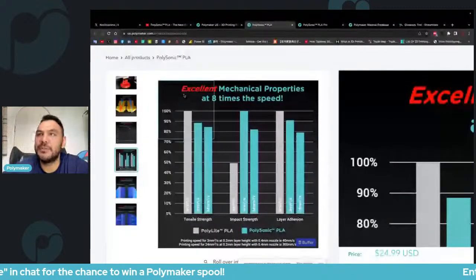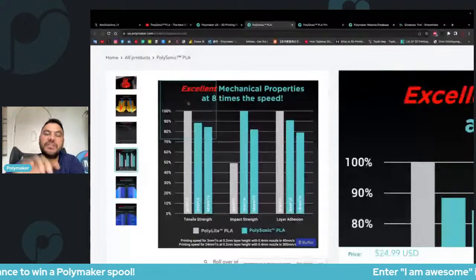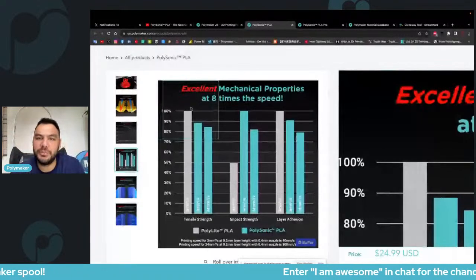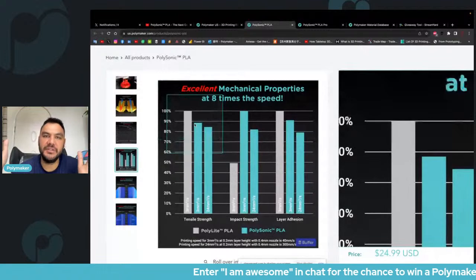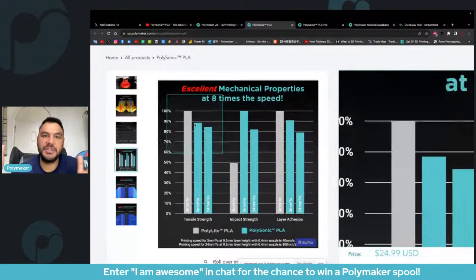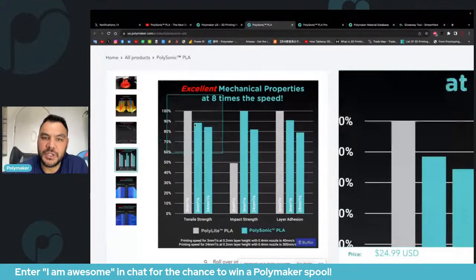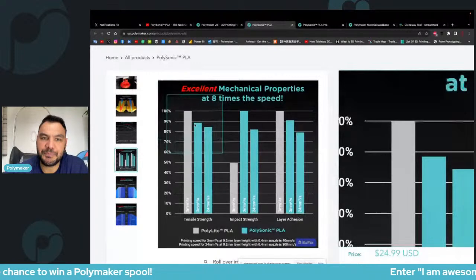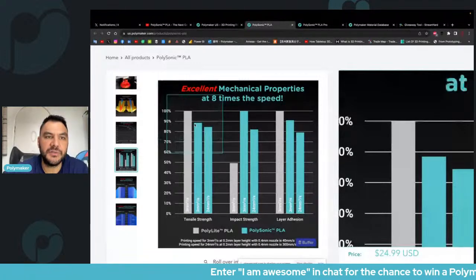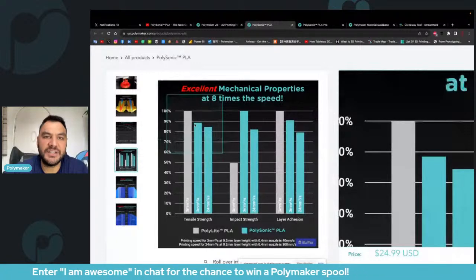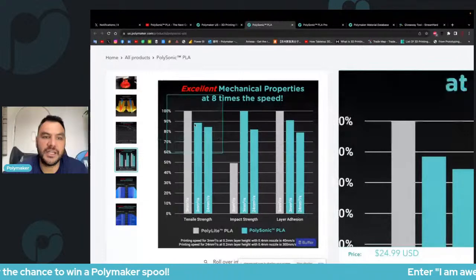But yeah, we wanted a material that, whatever speed you're printing at, within the speed range, has very similar mechanical properties. We maintain around 80%, always more than 80%. That's the definition: flowability, formability, functionality. Flowability, we meet the criteria because the maximum flow is 29 millimeter cube per second. And actually, I wrote everything here.